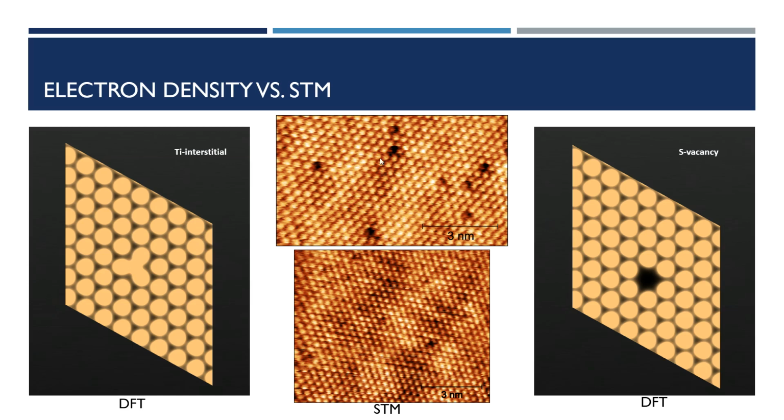And in addition, we did mention earlier that vacancies are not predicted to occur given our methodology and our results. However, these samples were annealed prior to the scanning, and as such, that additional energy could be the catalyst to cause these less likely defects to occur. And regardless, when scanning, we are pretty certain that these are vacancies.